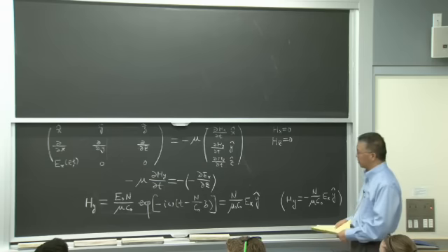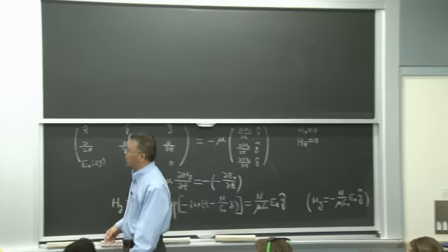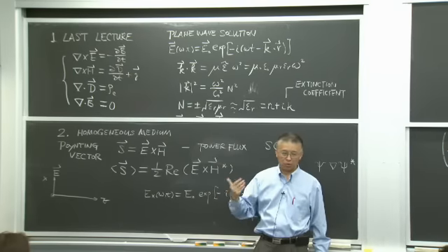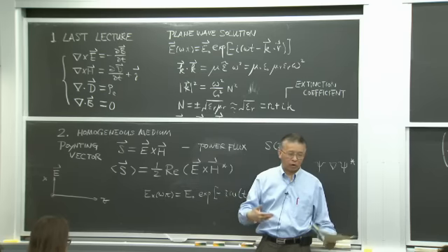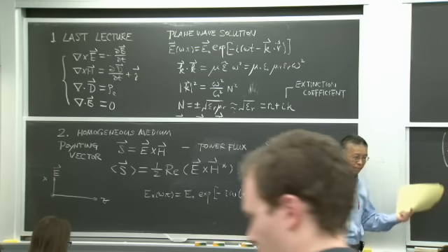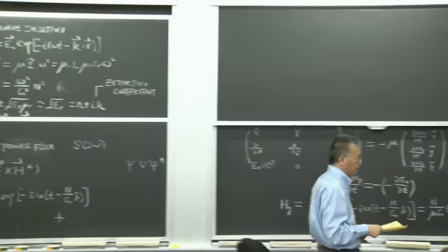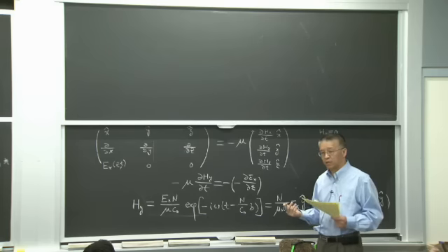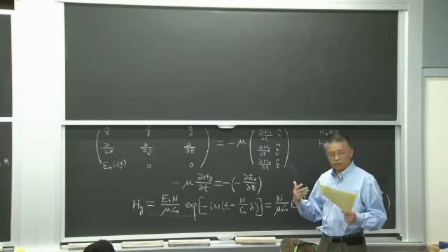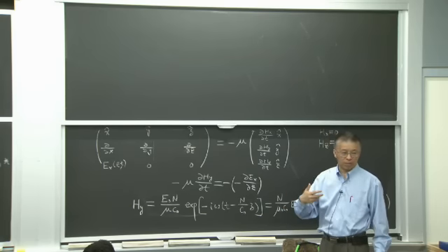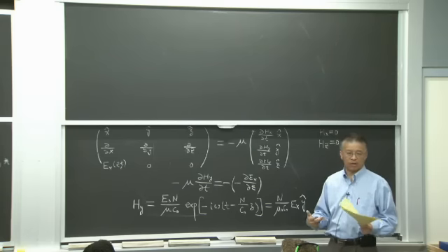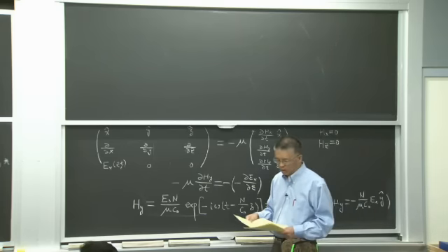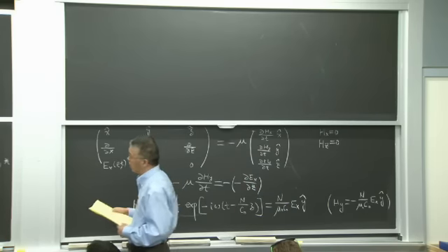But the later materials all have epsilon and mu pretty close to vacuum, so epsilon and mu r is 1. Normally people say that's just an academic exercise, until in the 90s people started to make artificial structures that have a magnetic resonance, so the magnetic response resists the external magnetic field, and that could generate a negative mu. In this case, you can design material with both epsilon and mu negative together, and the index becomes negative.